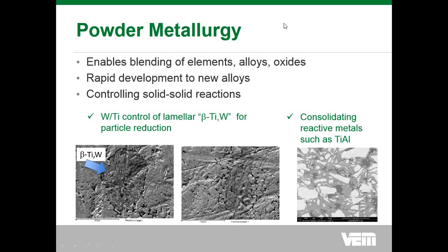Powder metallurgy, another application, is in thin film packaging or flip chip packaging, for instance. Chrome copper has been used as an underbump metallurgy. Chrome and copper do not lend themselves to a melt and cast. You can see the wide variation in the melting point from the phase diagram. So what can we do? If I want a chrome copper target, I can use powder metallurgy, taking copper and chrome, blending them, the copper being soft, and through the pressing process, we will actually encapsulate the chrome, making for a high density, high performance sputtering target material.